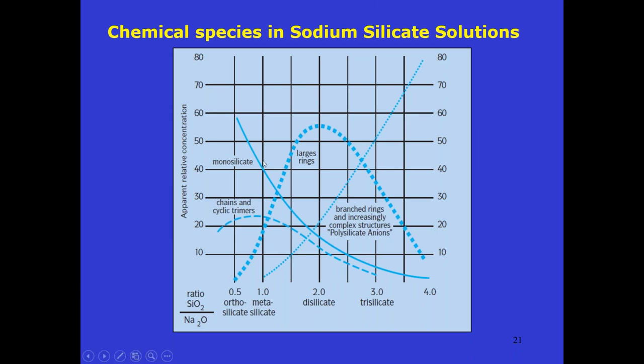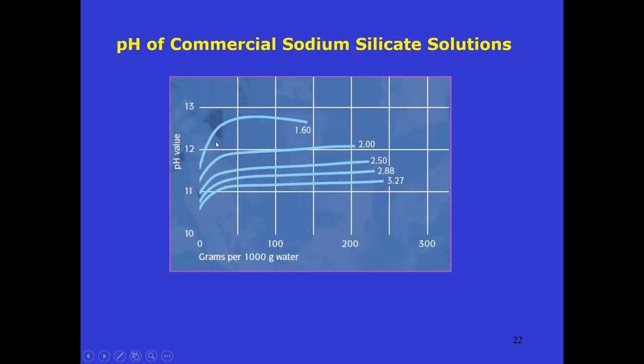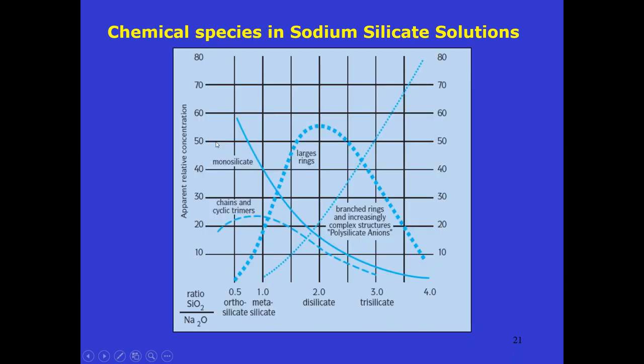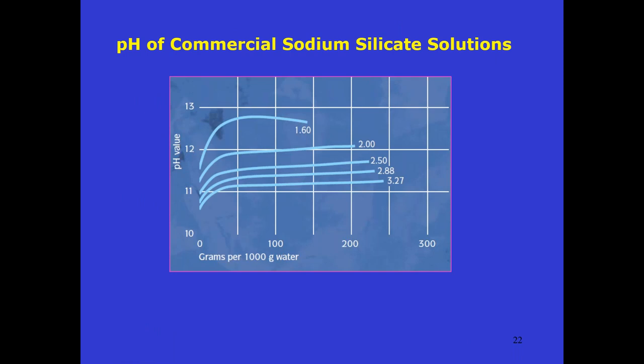So we must remember that this ratio is important, and we must calculate this ratio for the final solution you have made. Nobody is calculating it in India, which is not correct. We should calculate it so that we get a feeling of what kind of species we may be having. Now, depending on the weight ratio, the pH will change. When the weight ratio is lower, pH is higher. You can see here 3.2, and pH will go on increasing. But you can see pH is only from 11 to 13, not much change.